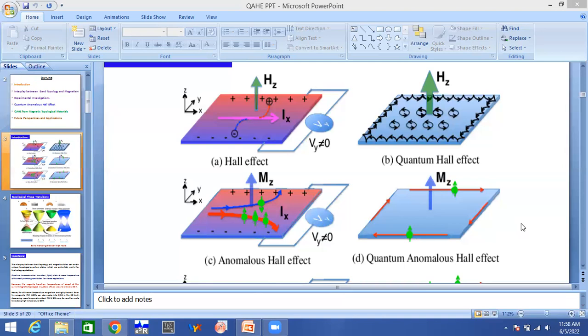Interface. So what he did, he put it in a very strong magnetic field in a perpendicular way at a very low enough temperature. Let's suppose at 2 Kelvin, 1 Kelvin. Millikelvin is now realized around 2000, but that time it was not available. And the field he introduced was 30 Tesla by capacitor discharge method.